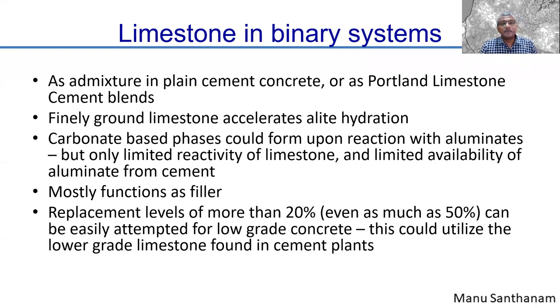Now, as I said earlier, in binary systems, that means just as a replacement of the cement, you can use it in ordinary Portland cement up to 5% as a performance improver, or as a major addition in Portland limestone cement blends. What does this finely ground limestone do? Finely ground limestone accelerates the hydration of the component of cement that is present in largest quantity, that is alite or C3S. Okay? C3S hydration gets accelerated in the presence of limestone. And the carbonate-based phases, see, limestone is calcium carbonate, some part of it is soluble.